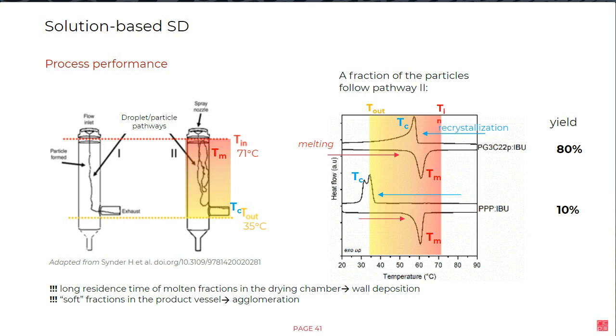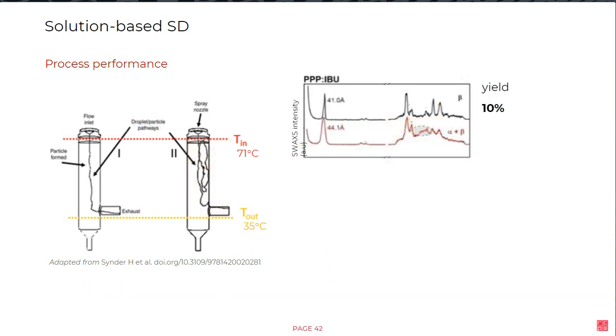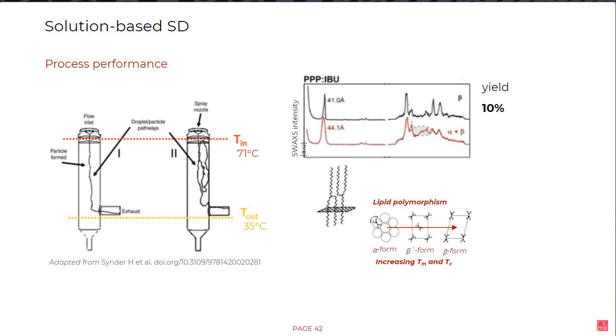I want to point out here that it's quite easy screening to use the DSC with a pre-formulation and to look at melting temperature, crystallization, and so on in order to choose correctly the inlet and the outlet temperatures. And I just want to explain why they have such a different behavior between melting and crystallization. Actually, the answer is very short. Tripalmitin suffers polymorphism, meaning that the beta form with the highest melting point will be molten in the inlet, and then it will try to recrystallize in the alpha form, which has a low melting point and a low crystallization temperature. And that's why we have such a problematic process.